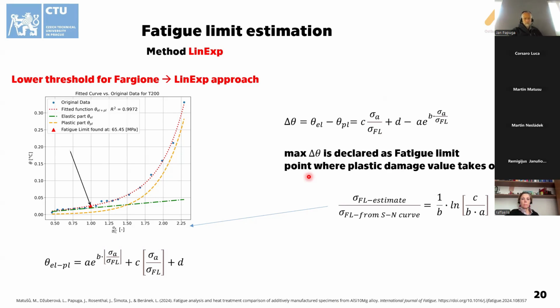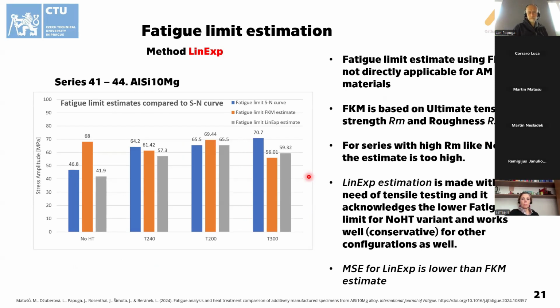We can discuss it further, but this comes with some problems. I tried to compare it with the FKM guidelines, which is quite a useful tool for fatigue life assessment, although it's not directly applicable to additively manufactured materials. I used the FKM guidelines for cast aluminum, which is much closer than wrought aluminum in my opinion. What FKM uses is the ultimate tensile strength and Rz, the roughness of the specimen. And here you can see that the linear exponential method, as we call it, is conservative in all of the cases for the 41 to 44 series, and here it's nearly perfect.